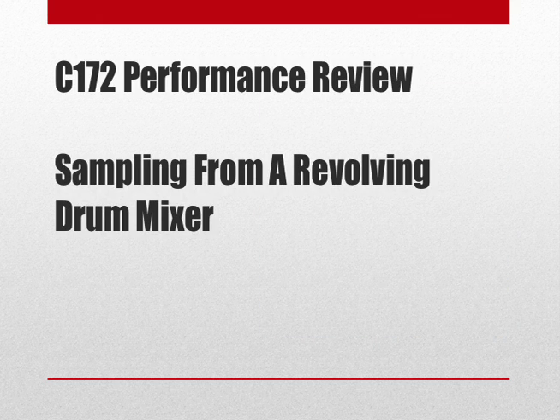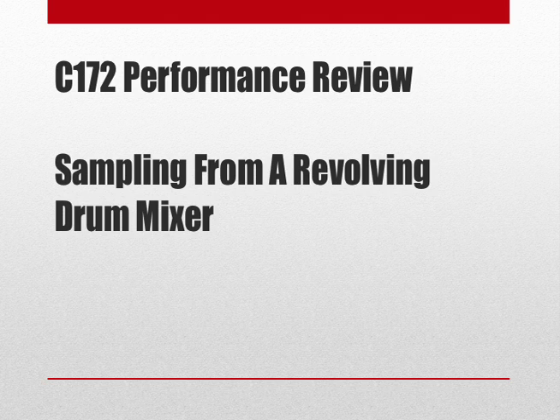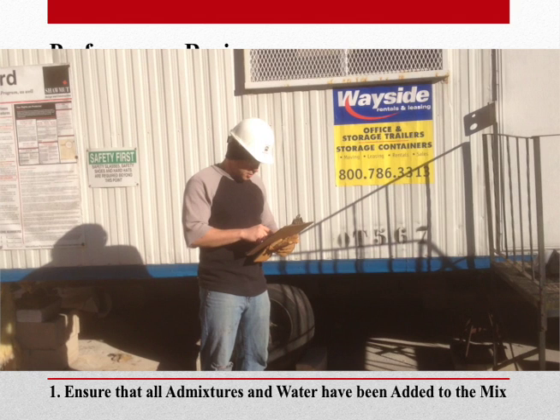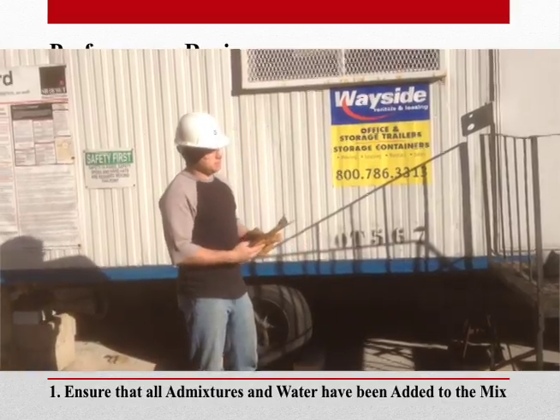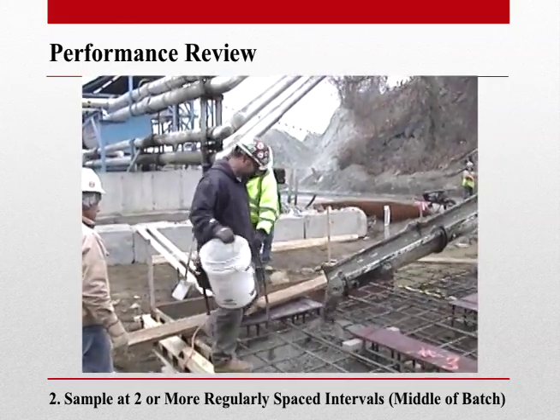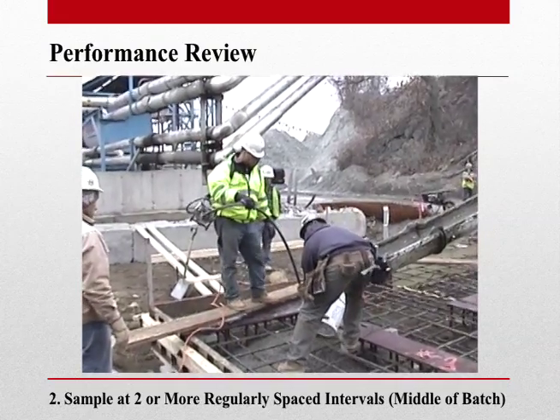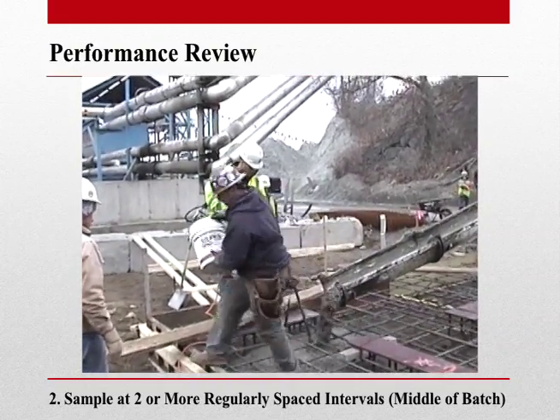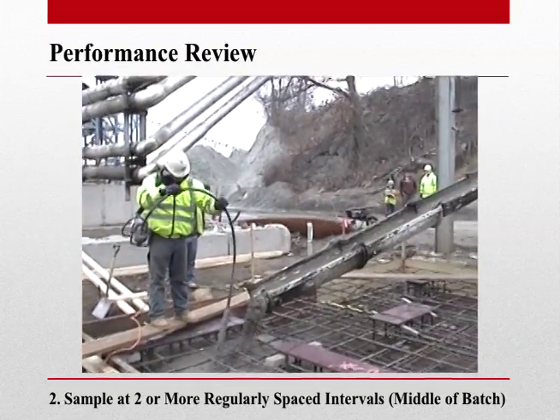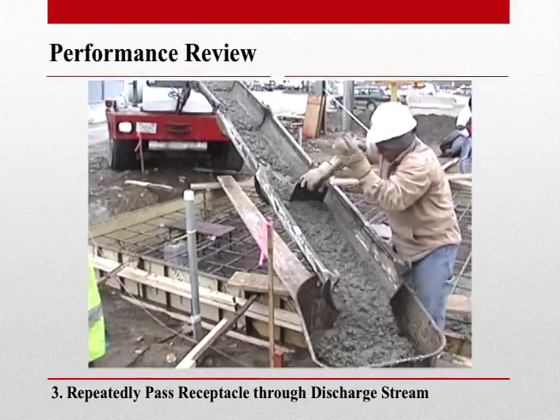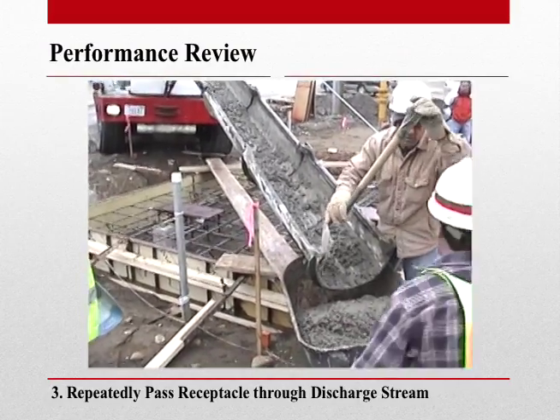Now that we have an understanding of the requirements and procedures of ASTM C 172, let's go through a detailed performance review of sampling from a revolving drum mixer. First, we want to always ensure that all of the water and admixtures have been added to the concrete. We now want to obtain our sample at two or more regularly spaced intervals from the middle of the batch.